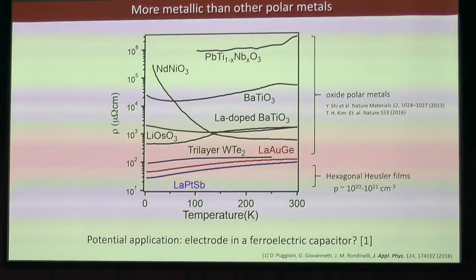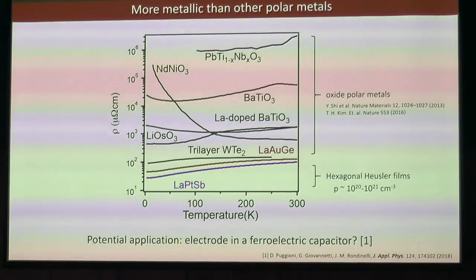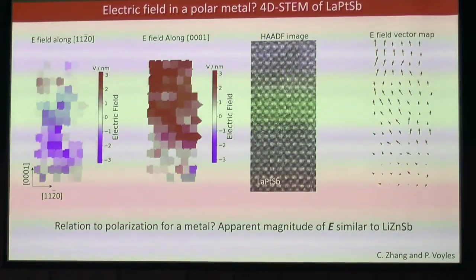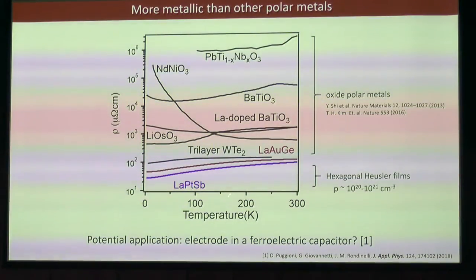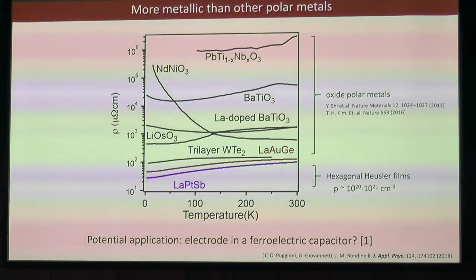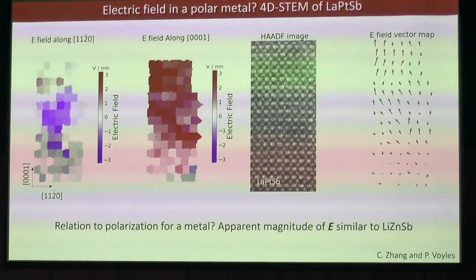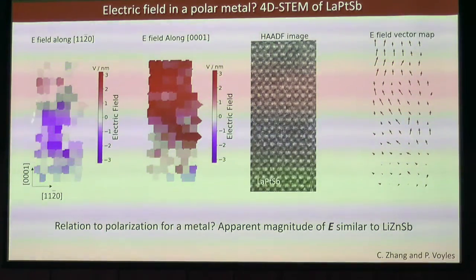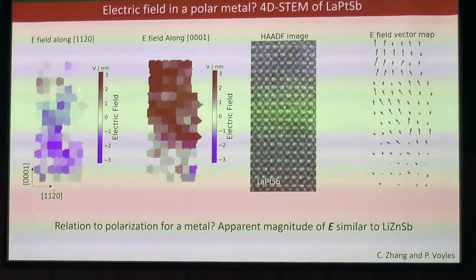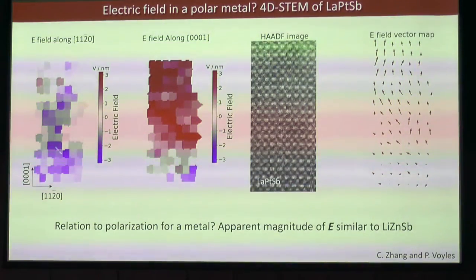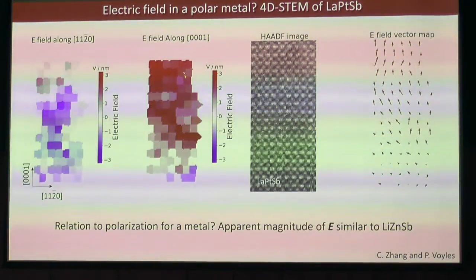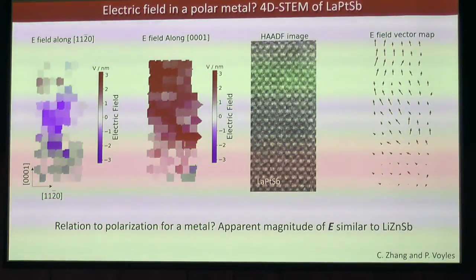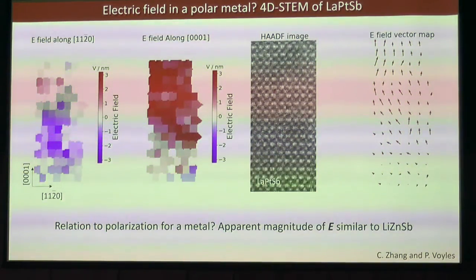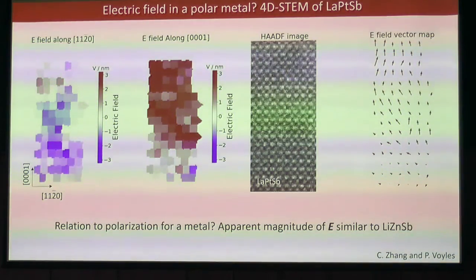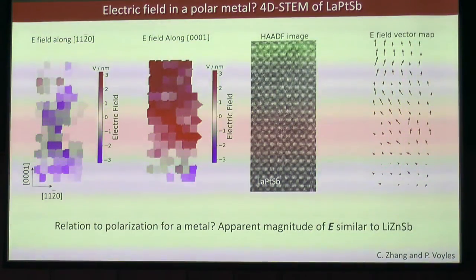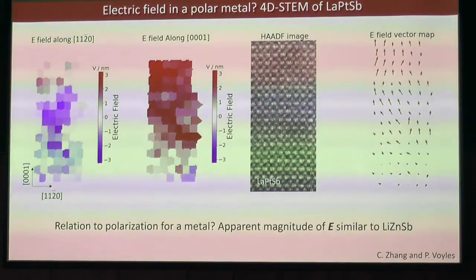but that's not the original reason why we were interested in them. Okay, so the original reason was to ask, stepping back, you can do 4D STEM on these compounds as well, and that's what we've done here. Okay, so here's the HAADF STEM image. Here's the 4D STEM image where we're plotting momentum transfer, or apparent electric field, in plane and apparent electric field out of plane. So this is the direction where there's the structural polarization. And we measure apparent magnitudes of electric field that are comparable to what we saw for the insulating lithium zinc antimony.